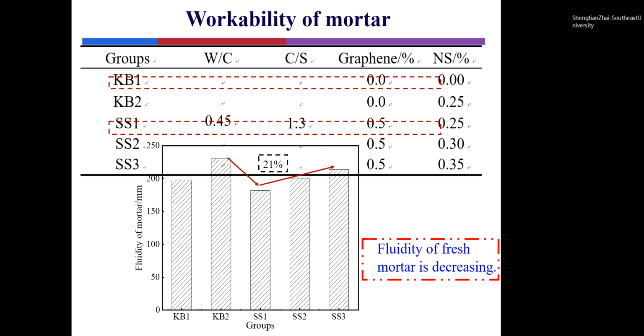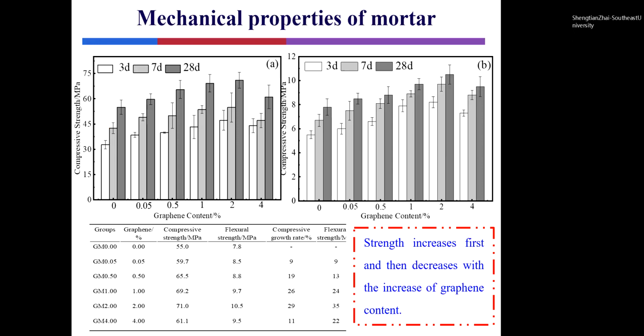This picture shows the fluidity of fresh mortar. The result shows that the fluidity of the mortar is decreasing with the addition of the graphene. This is mainly due to the large specific surface area of the graphene absorbing a lot of water. This picture shows the mechanical properties of the mortar with the different graphene contents at 3, 7, and 28 days. We can see that the compressive and flexural strengths show the first increase and then decrease tendency with the increase of the graphene content. In addition, the effect of the graphene content on the early age of the strength is the most significant.